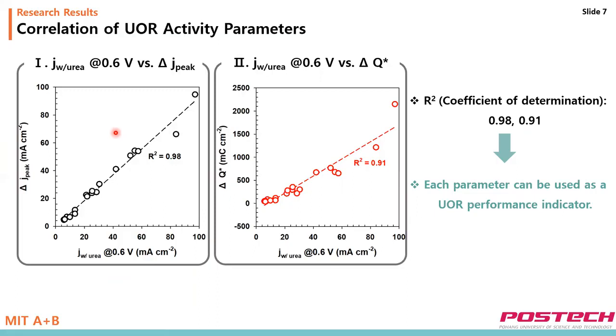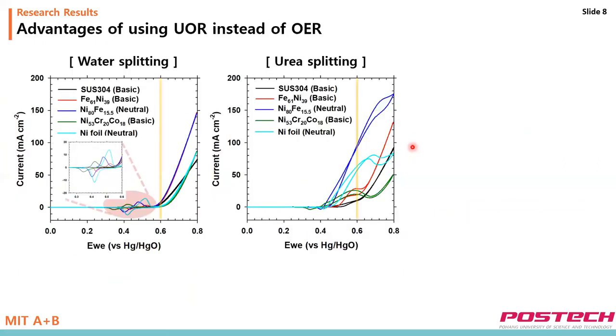This linear regression implies that all parameters are correlated with others. In short, use of these 3 parameters is effective to explain the UOR activity. To find out in more detail why UOR is more energy efficient than OER, the graph shows the highest activity of treated alloy depending on other source material respectively.